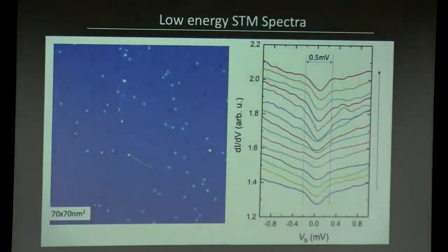So now let's look there. This is a plus minus 1 millivolt spectrum. And if you take a line cut, you see an extremely strange looking shallow superconducting gap that has no coherence peaks. You don't immediately know that this is actually a superconducting gap.